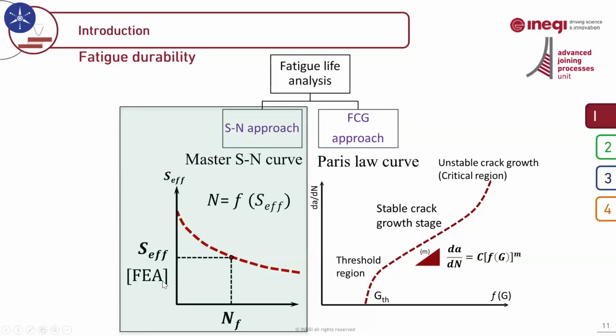And with the help of finite element analysis, plus this master curve and an effective parameter, or fatigue parameter, that we should develop or select correctly, we will be able to predict the fatigue life of adhesive joints in real practice. We also have another approach, still based on SN but without this master curve, which gives us ideas about the fatigue of adhesive joints, but I will talk about it shortly. On the other side, we have the fatigue crack growth approach.